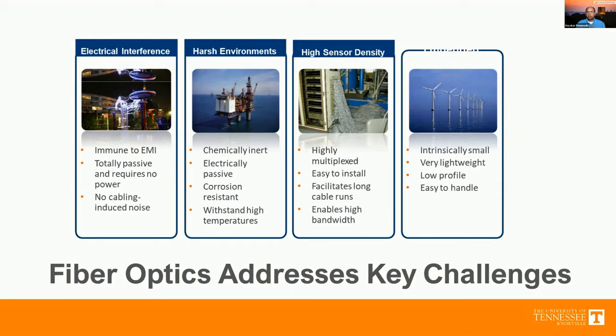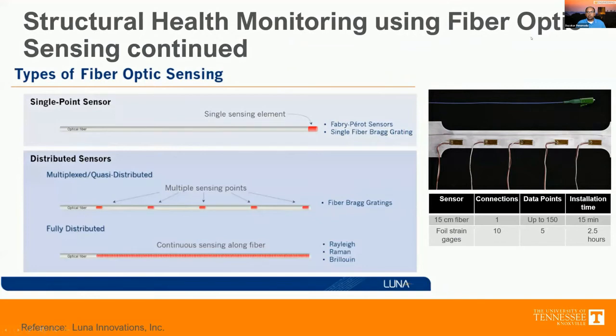I think Rick showed in his wonderful presentation how they were using spatially resolved temperature sensing to monitor how the temperature was varying as they were depositing material. And similar to that, in addition to temperature, for a lot of these bridge structures, we need to measure mechanical strains as well as environmental variables like the relative humidity and displacement associated with flexure, and also some special sensing that's needed for monitoring in-plane and interlaminar shear performances. So we have very effectively utilized this sensing technology to date.